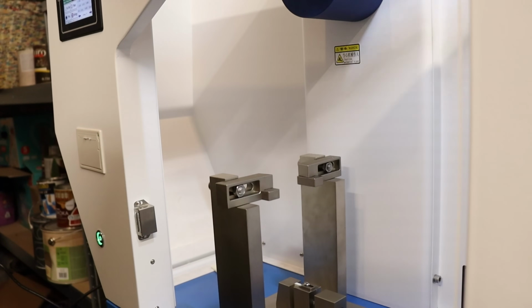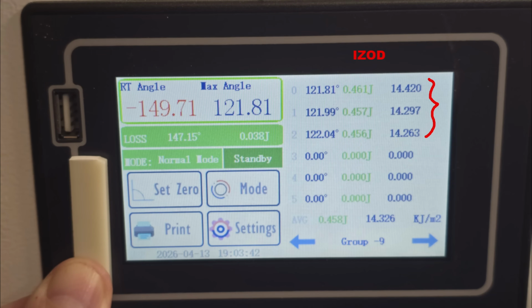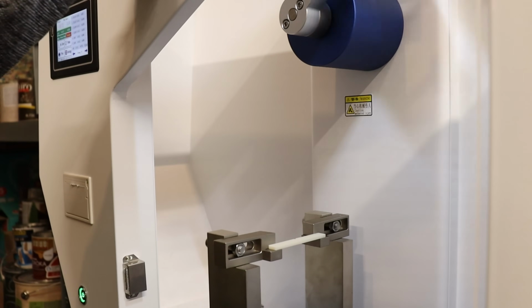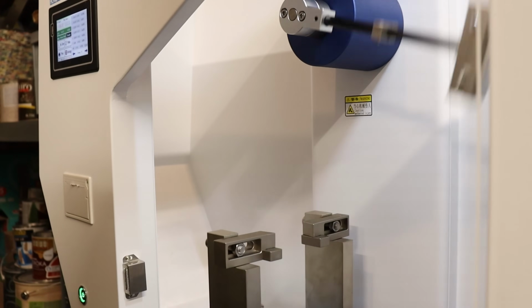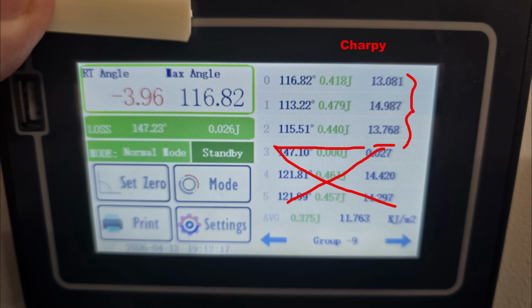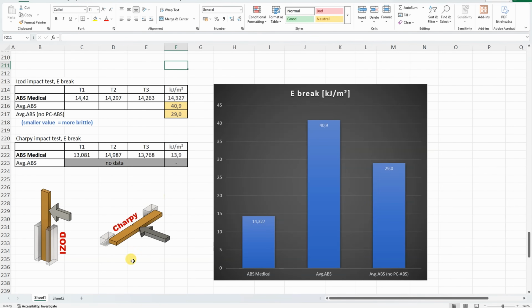The object is located in vertical position, and results from 3 measurings. Charpy, horizontal, supported from 2 sides, and results from 3 measurings. For the Charpy I don't have enough data, but for the ISO I have a lot of materials for the comparison. Now, average ABS, but in this number some ABS PC blends are also included, and if I exclude them, then we have this number. It's still bigger compared to this ABS Medical, so it is more brittle compared to the average ABS, but still far tougher compared to any PLA or PETG material.